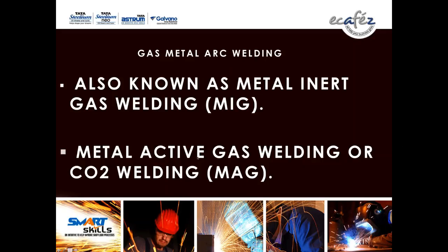You can get spray transfer by using argon CO2 only. You cannot get spray transfer with CO2 alone. CO2 cannot give you the best welding by MIG process. If you go for argon CO2, then you can get the spray transfer as well as high mechanical properties, a higher bead appearance, and a very good weld profile.